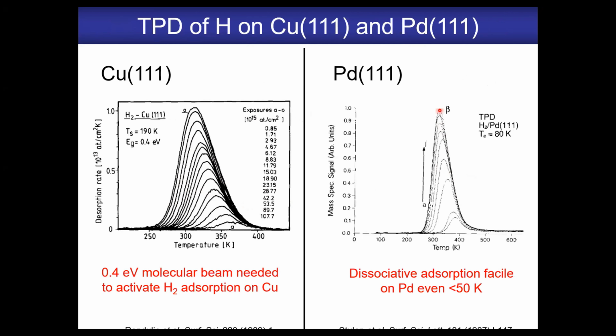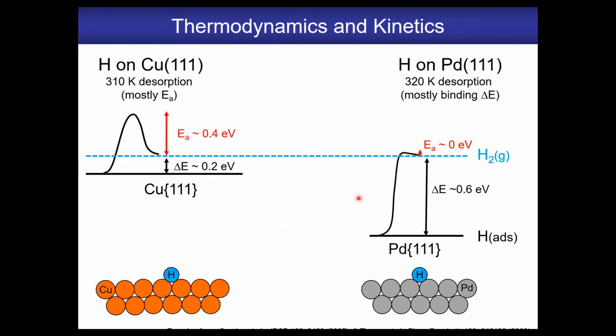Whereas on palladium, easy to dissociate molecular hydrogen. You can get plenty on there below 100 Kelvin, and again, second order desorption. But if you looked at these two temperature programmed desorptions, you would see that the temperature at which the hydrogen comes off the surface is almost the same, and you would naively think the reactivity of these two metals towards hydrogen was almost identical. But what we know from other measurements, beam measurements and theory, is that hydrogen dissociation has this high barrier on copper, but once the hydrogen's dissociated, the hydrogen atoms are bonded weakly to copper. Whereas in palladium, there's almost no dissociation barrier, but then the hydrogen atoms are bonded much stronger to palladium.